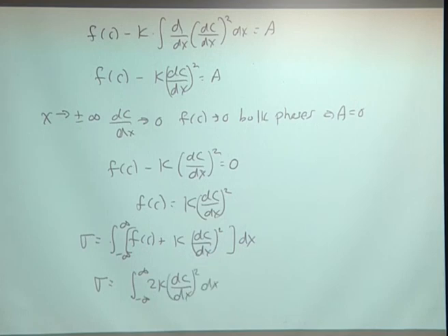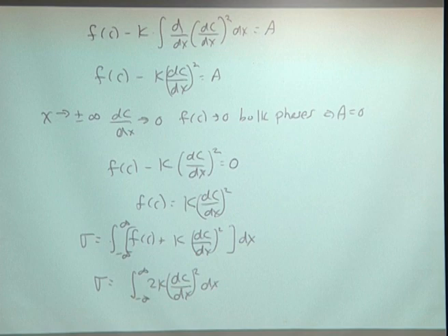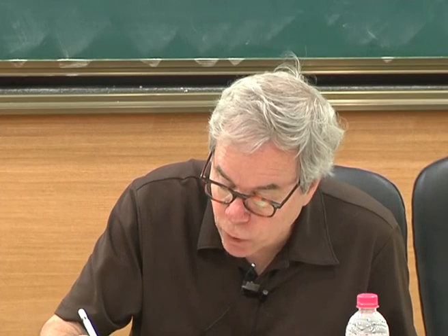dx. And so this equation here turns out to be quite useful in a phase field model, because basically it says that I don't need the free energy function in order to get the interfacial energy, right? It's independent of the free energy function, which is kind of cool, and it only depends upon the derivative. And so that's very helpful when you derive your phase field models and you want to compute the interfacial energies.